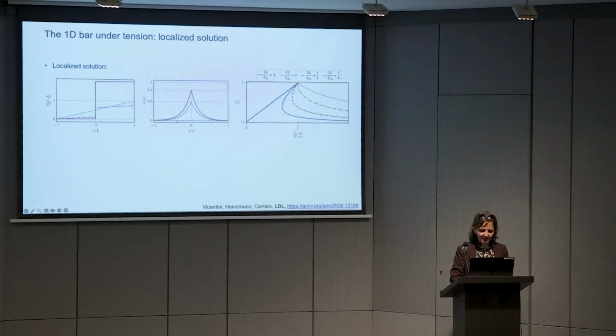Then we computed the localized solution. The localized solution has this jump in the displacement, and has the profile for the damage. The interesting difference with respect to the standard model is that now the jump in the displacement depends on the value of the damage in the, let's say, point that is damaging, and you have a cohesive response in the sense that you do not jump directly to two pieces of the bar separated, but you have a cohesive response. So you don't get the full damage until the jump reaches really large values.